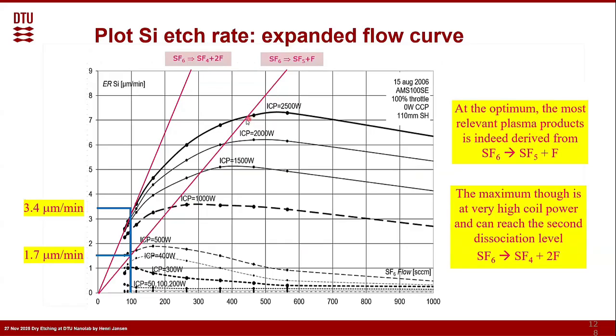And this is typically preferable, because here we are not using too much power. It could be that it gets so warm and hot that, although you create a lot of fluorine radicals, due to the high power you also create a lot of temperature, and maybe you have a selectivity problem with your resist, etc. So you rather stick where you are very efficient but still at relatively low powers. So it could be more advisable to stick at the maximum of this curve here, where you really perform in a neat way.